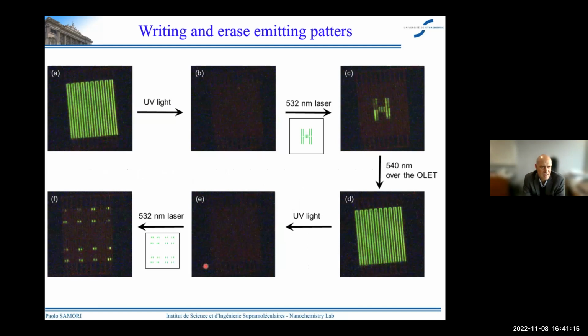Then we can show that we can write and erase patterns. So we start from the case where the diarylethene is blended with the green emitting material, and you can see light emission coming from the interdigitated pattern. We illuminate with UV light the whole device, and therefore we create traps and we quench the luminescence. Everything in B is black. Then we can irradiate, let's say with our laser, at 532 nanometers, an H symbol. In this way, we can recover luminescence in the irradiated part of the sample. We can illuminate with visible light the entire sample and recover the light emission from the entire device. We can again illuminate with UV light to quench the emission again in E.